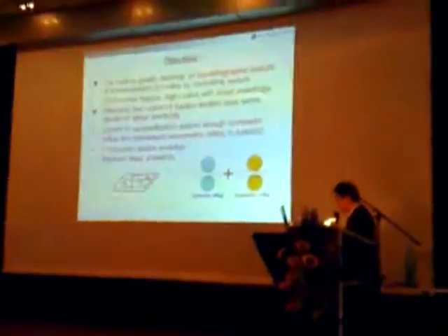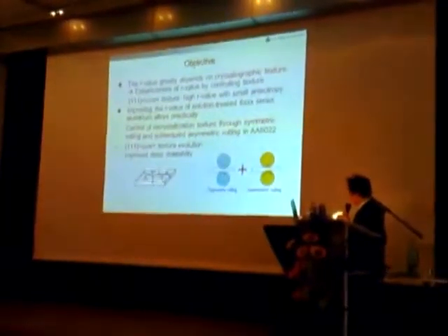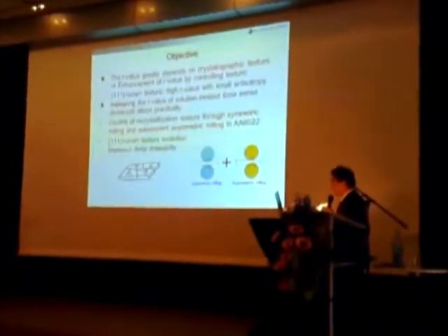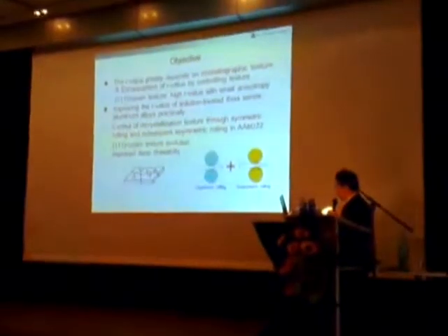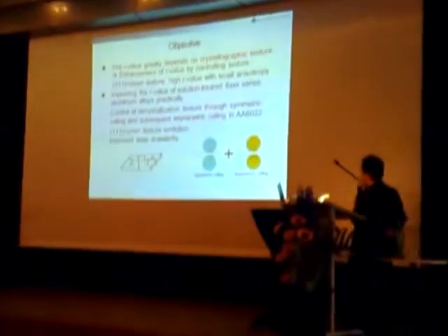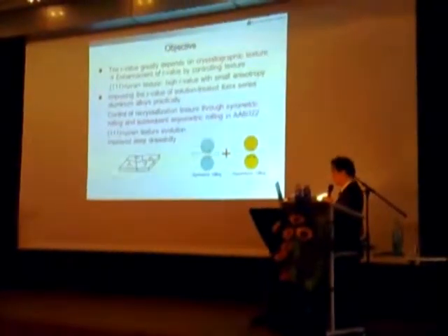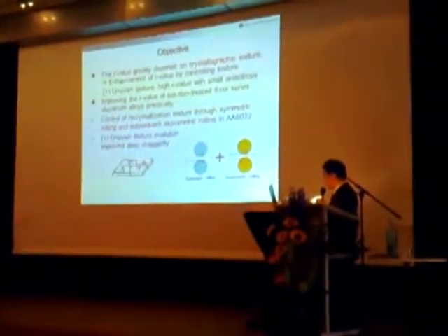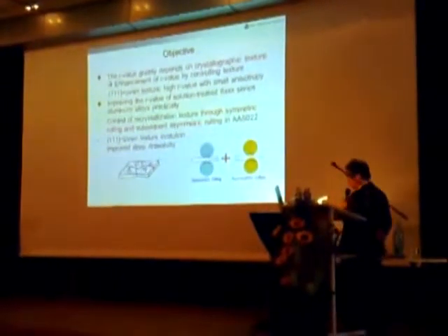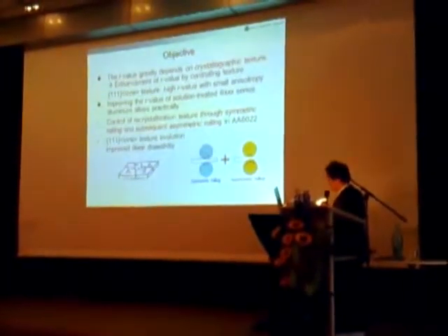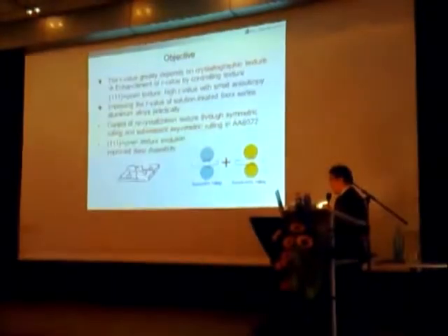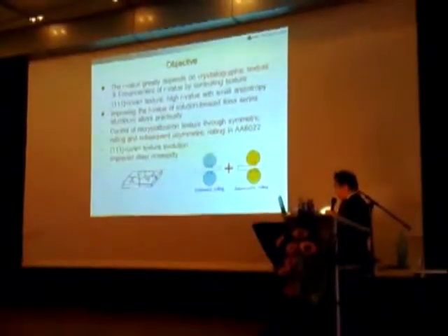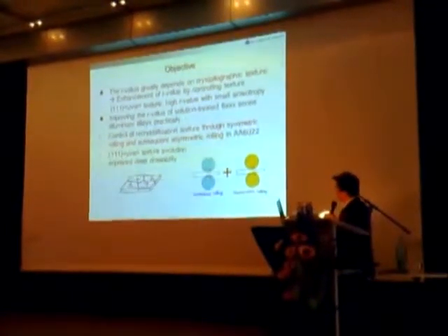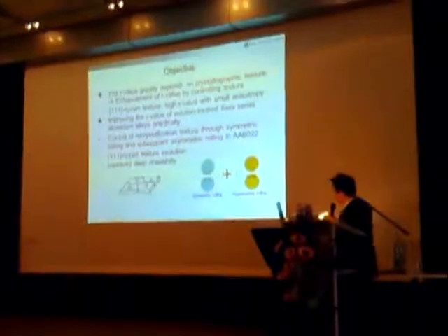Texture component has high R value with small anisotropy. The aim of this work is to improve the R value of solution treated 6000 series aluminum alloy by controlling recrystallization texture through symmetric rolling and subsequent asymmetric rolling like this. And we obtain the 111 texture evolution.